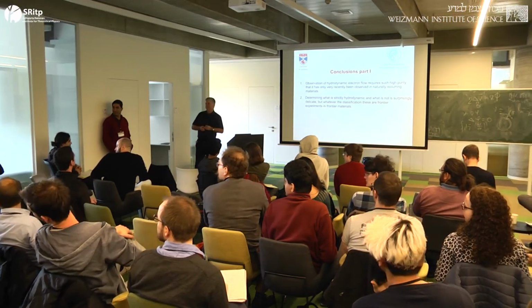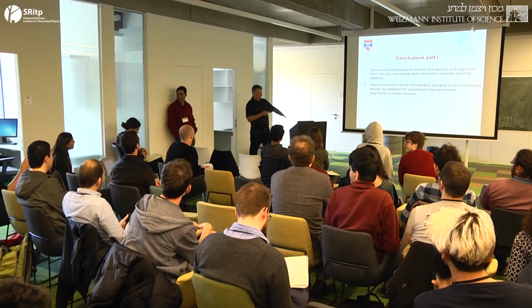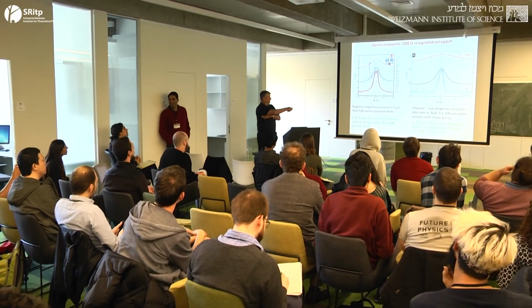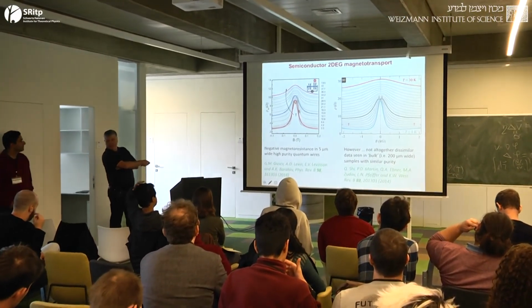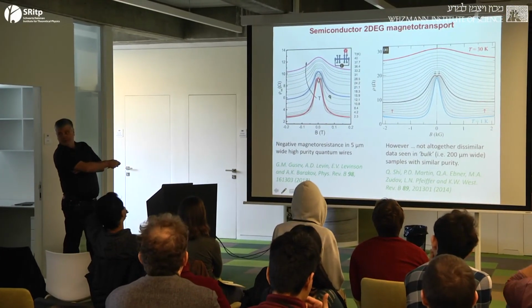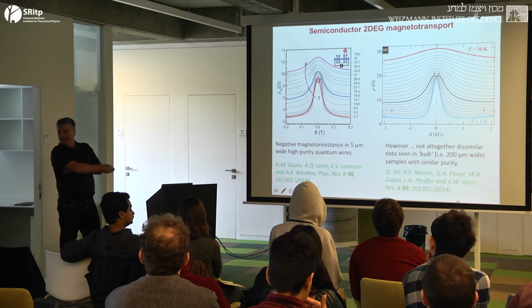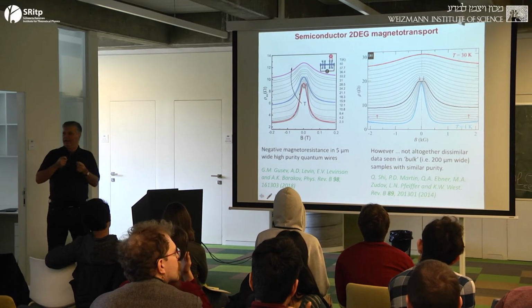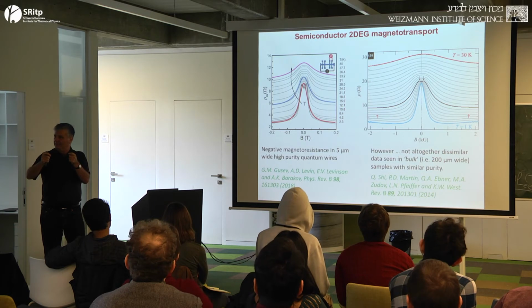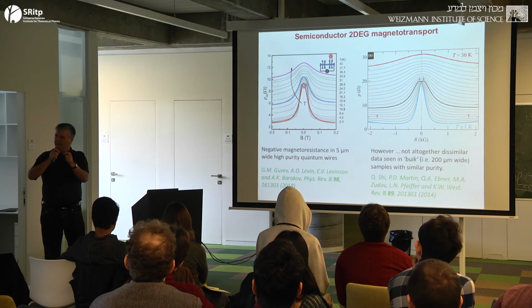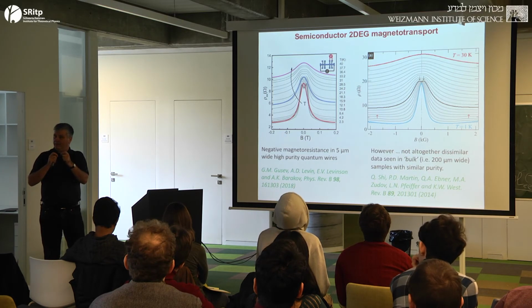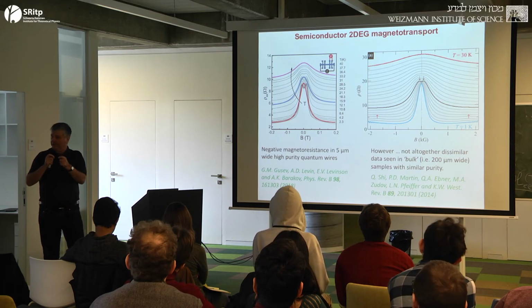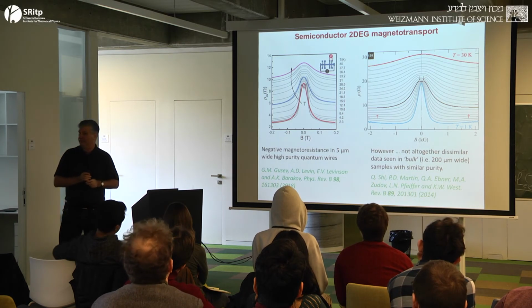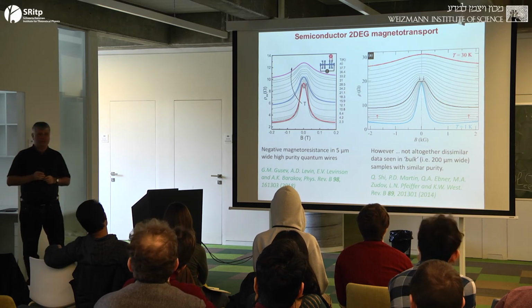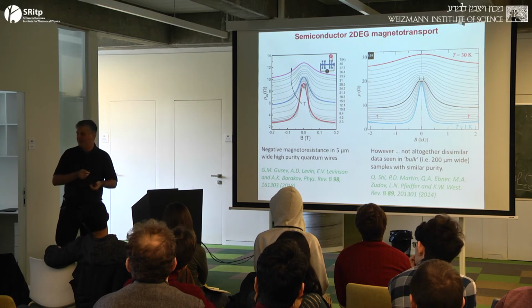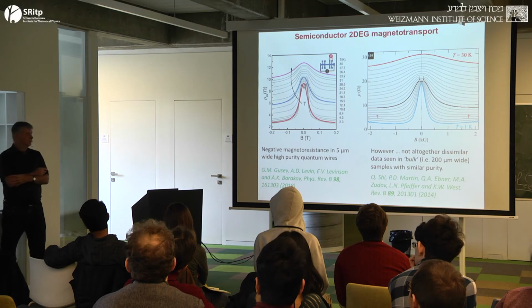I did. How would you measure that? Well, good. If your eyesight's very good, you'll see that here's an example, and there are many examples of this, where you start at a certain resistivity at zero field, and you then go through a peak before going down. What you're charting with that field measurement is the transition from the ballistic to the hydrodynamic regime, essentially. But the strength of the peak must depend on the boundary scattering. So it seems to me it would be possible to use known models of boundary conditions and those measurements as a caliper to determine what sort of boundary scattering you've got. I know that Shahal and his group have thought a hell of a lot about this, and I'm guessing that we're going to hear something more cerebral on this from him later on, or from his group, from Joey. You can read it out of this here tomorrow.